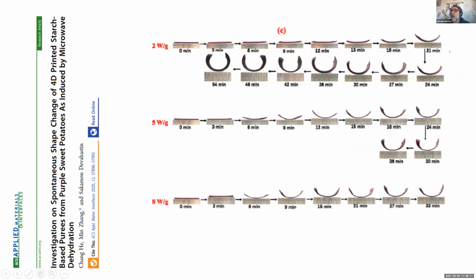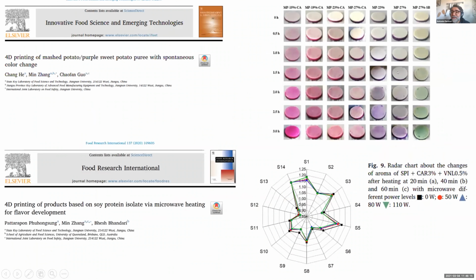Also, 4D printing in terms of color, where the activator is the pH. In this case, the researchers tried to create a multi-layer material. Each layer has different pH, and when 2 layers are in contact, there are some colorants inside that change color over time. And also really interesting is that it is possible in 4D printing to create flavor development, a change in flavor activated again by microwave heating. So if I apply a different microwave power, maybe we are able to change the flavor, that is the volatile compounds.